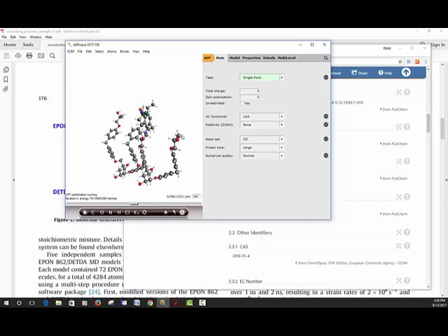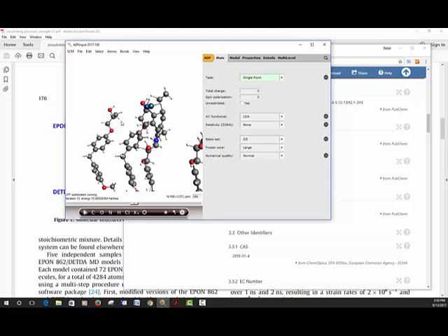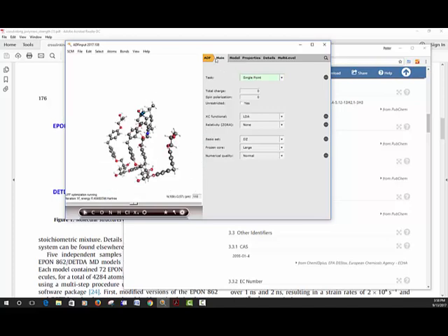And then eventually, when you've done building your structure, you want to make sure that you also hydrogenate or make end caps at your group. So these are still radical sites here. This is a CH2 group at this end, and that's a CH2 group. So you want to cap that before you start running, for instance, your reactive molecular dynamic run to calculate whatever property you're interested in. So that concludes a little demo on how to do that.